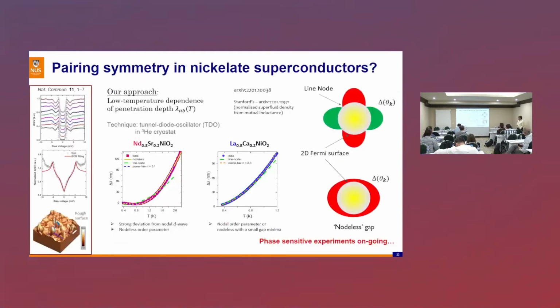So one of the questions, of course, is the pairing symmetry, and an experiment has been done before by STM in a group in China. As you can see here, at different locations on the same sample, you see this V-shape or U-shape feature in STM. So there are mixed conclusions from here: either there is really an actual mixture of the symmetry, or simply because of the inhomogeneity of the samples at the different locations.